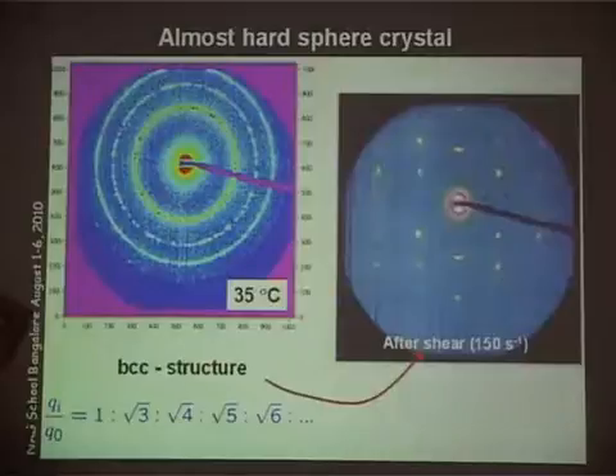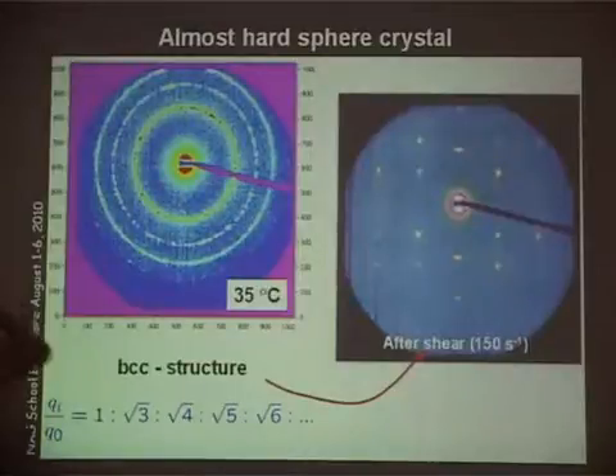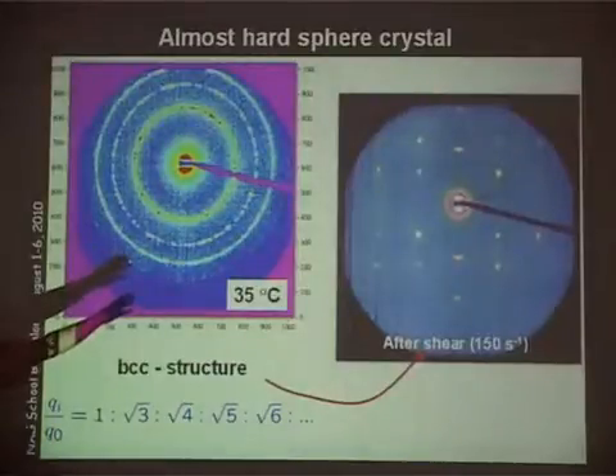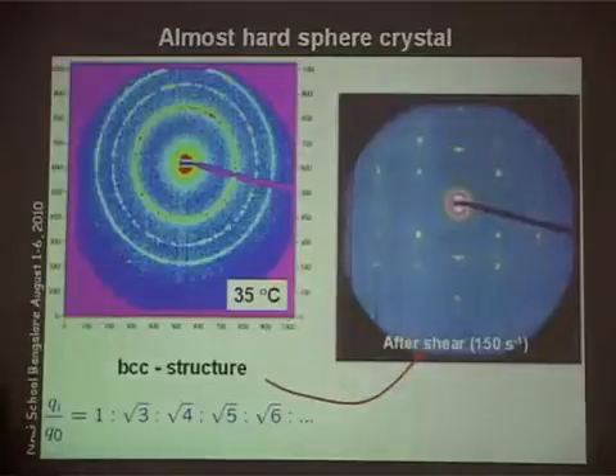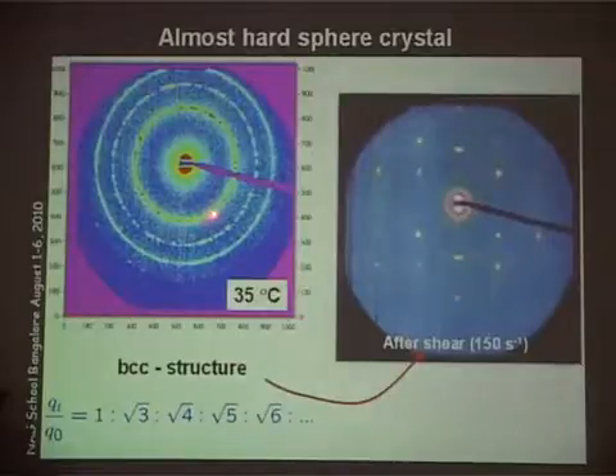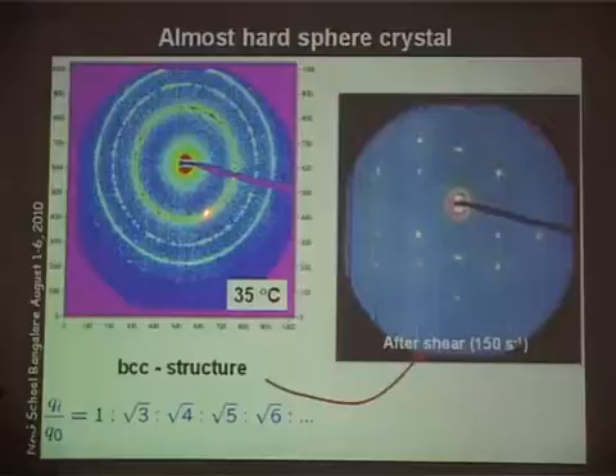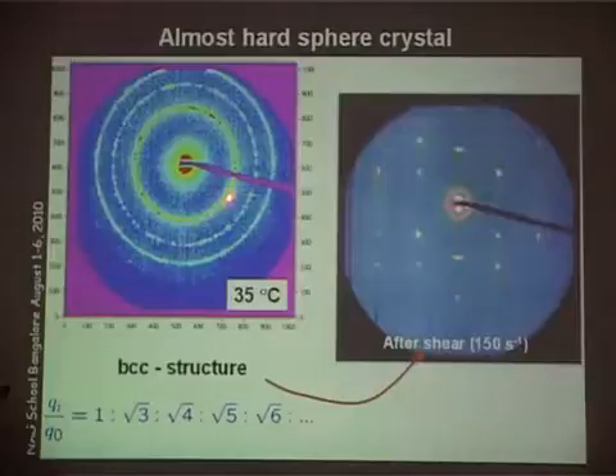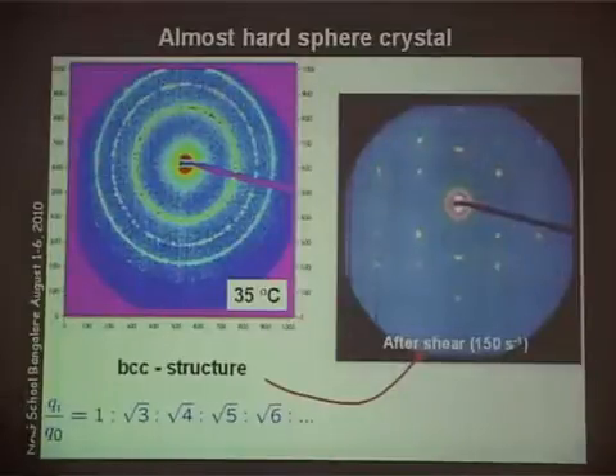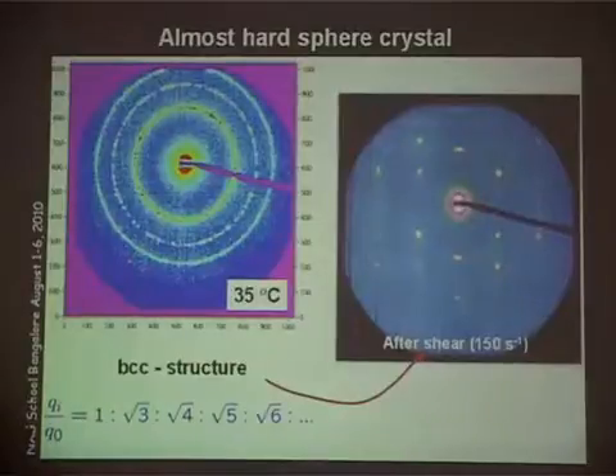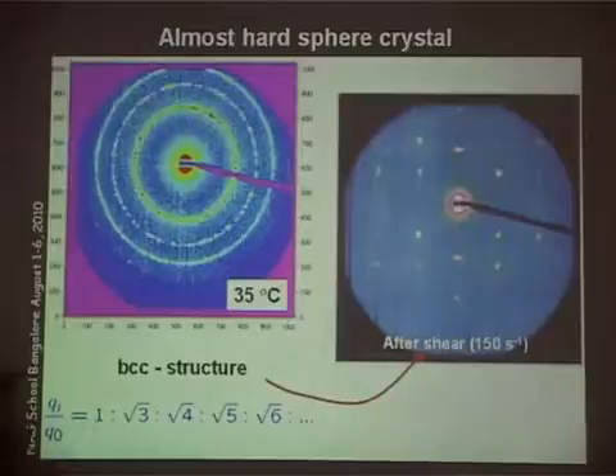Is that correct? Yes, for hours. Hours, I see. Half a day, days. I don't have so much time at the synchrotron, but it does. You go away over lunch, you take another shot, exactly the same. Some of these, when you wait long enough, you see are really a bit larger grains than others. They seem to coarsen and become bigger grains with time. But once I have this, it's very, very stable. It's like hair gel. When you feel the material in this situation, it's like hair gel.